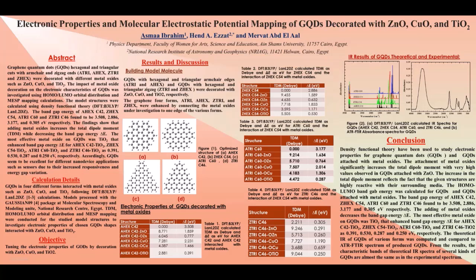The adding of metal oxide decreases the band gap energy. The most effective metal oxide for graphene quantum dots was titanium dioxide, which enhanced band gap energy.